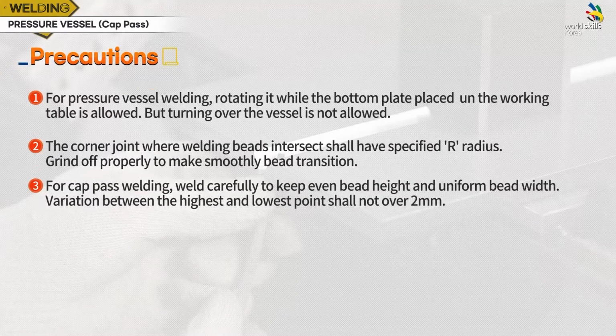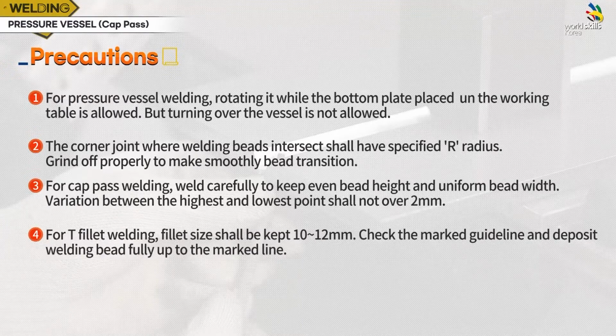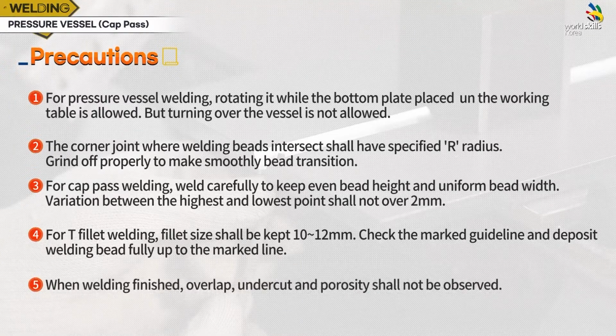Work carefully to ensure that the bead height and bead width of the cap pass come out uniformly. The difference between the highest bead height and the lowest bead height should not be more than 2 mm. For T-fillet welding, fillet size shall be kept 10 to 12 mm. Check the marked guideline and deposit welding bead fully up to the marked line. When welding is finished, overlap, undercut, and porosity shall not be observed.